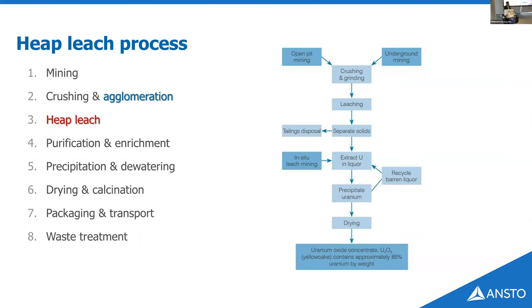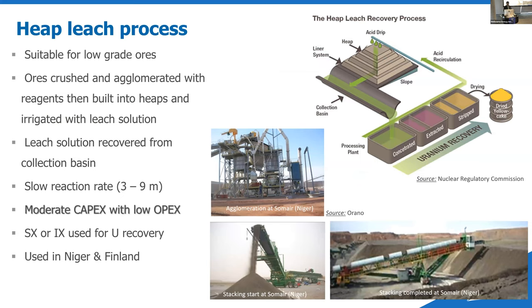So that was the conventional process. Heap leach. What is heap leach? If you look at the flow sheet that I had before, basically you're looking at all that put into a single step, okay? It's really suitable for low-grade material where the ore is crushed and then agglomerated and put onto heaps. Once it's made into a heap, you're irrigating the solution. The heap itself requires a liner underneath where the irrigated solution will collect. That solution is then sent to the process plant, and the uranium is recovered and the liquor sent back through.